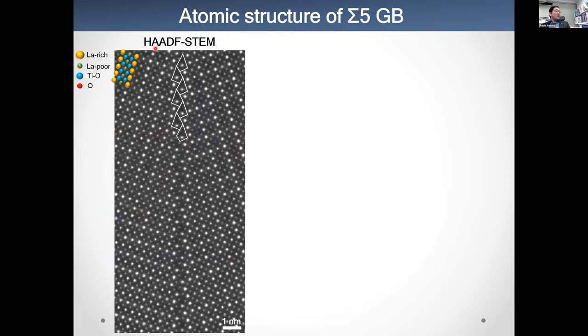So this is the HAADF image of the sigma 5 grain boundaries. You can see the bright columns as a layer. This is a lanthanum-rich layer, and this is a lanthanum-poor layer, and the lanthanum-rich layers are alternately located and form the grain boundaries. And the structure in it is in a zigzag manner, like that.